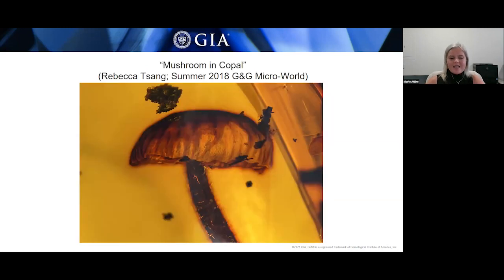So this was a 19 carat, about a 20 carat actually, copal. A copal is a natural resin that is much younger than amber. And this copal contained a very large, visible and very well preserved mushroom. And it's reported to be from Mexico. The cap of that mushroom was measured about 5.5 millimeters in diameter.